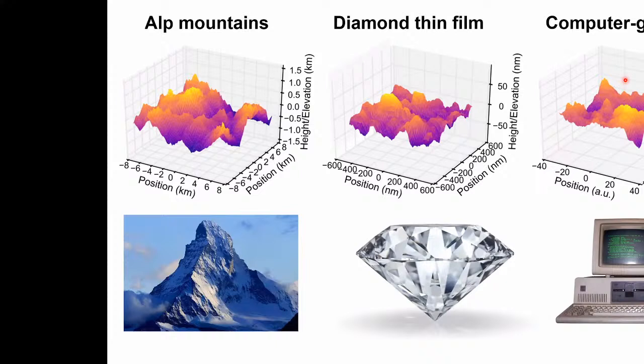So the goal of this exercise is to illustrate that, if I take something that is really large scale, this Alp mountain range, and I rescale the positions by a certain factor, and I rescale the heights by an appropriate factor, then I get something that is virtually, or statistically, indistinguishable from something like, for example, this ultra nanocrystalline diamond surface. That is a property that is called self-affine scaling, in this case, statistical self-affine scaling.